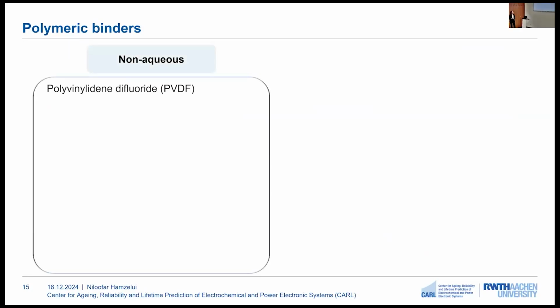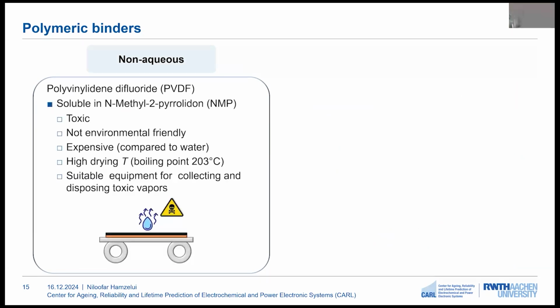In general, binders can be divided into two groups. Non-aqueous binders, such as PVDF, are commonly used in the anode and cathodes of lithium-ion batteries. PVDF can be dissolved in NMP solvent, which is a toxic solvent, and it requires a higher drying temperature for the electrode, and also it is more expensive. And suitable equipment is required for collecting these toxic vapors during the production of the battery and the drying process.